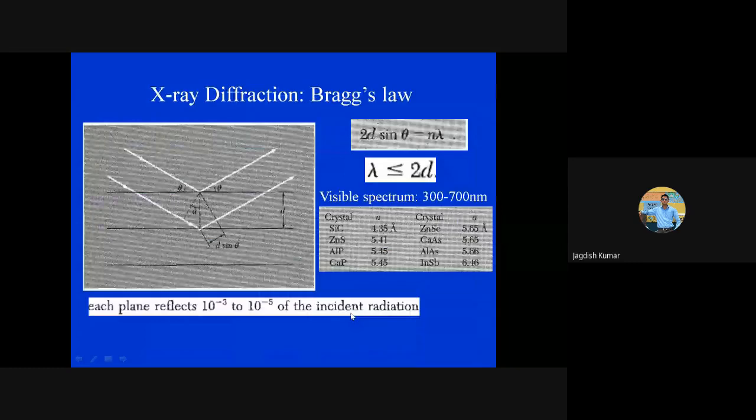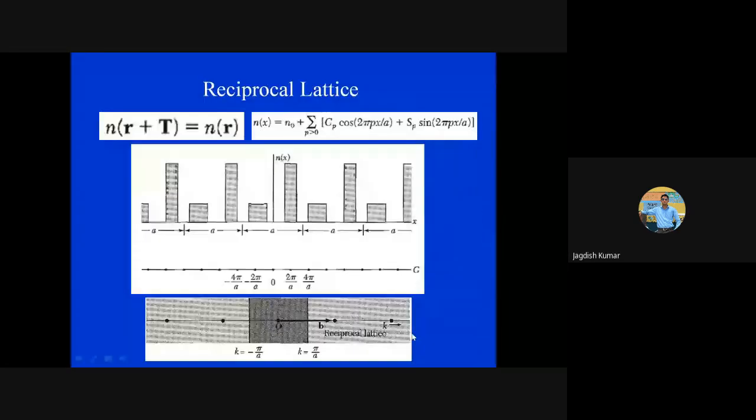Fine. So how do you go to the next Brillouin zone? Is it discussed here? No. Okay. How do you go to the next, second Brillouin zone? You have to connect this with the next neighbor and then draw another perpendicular bisector. And to this side as well, there will be another perpendicular bisector here. So this region, I mean, region between pi by a and plus 2 pi by a and minus pi by a and minus 2 pi by a, these two regions constitute the second Brillouin zone, and so on. Similarly, you can have third, fourth, fifth Brillouin zone in 1D lattice.